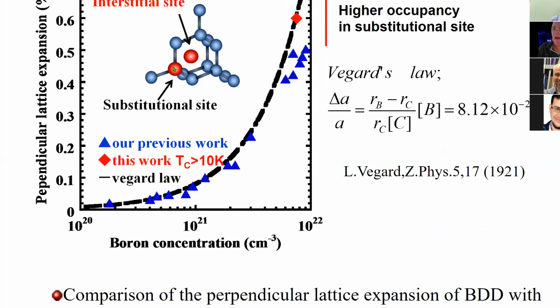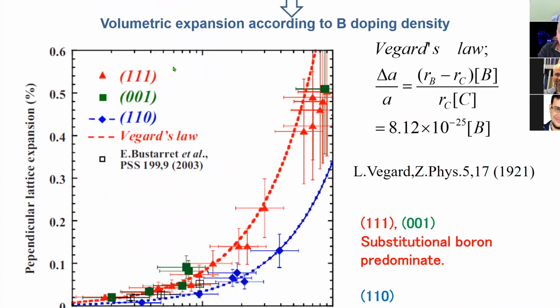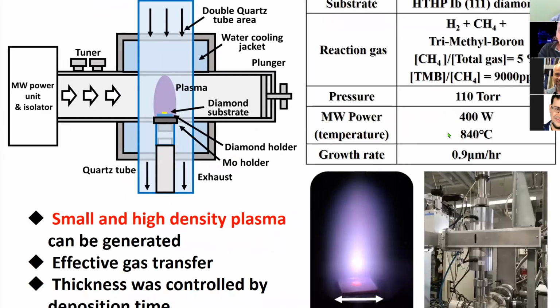We don't anneal, but I didn't show you the temperature - sorry, the growth temperature is 800 degrees or more. So it is not ion implantation, because annealing normally we use for ion implantation, but this impurity is just incorporated during the growth of the diamond.